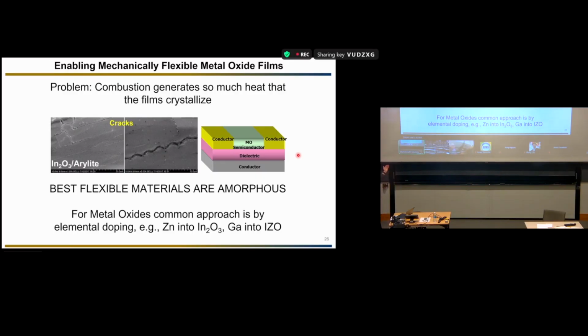One of the things we have been interested in is to make some of this oxide at least mechanically bendable. And the typical way to make oxide film more tolerable to deformation is to make them amorphous. IGZO is much better than indium oxide, for example. And why? Because you take your matrix and you start throwing in a lot of elements, and this creates disorder, you depress the crystallization temperature. We wanted to do it in a different way.